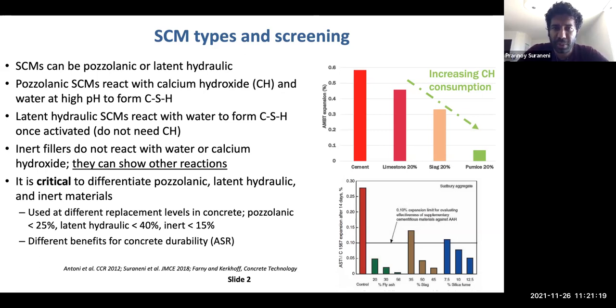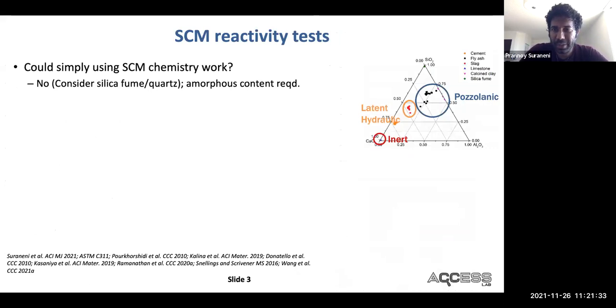But ultimately, you really want to separate out, when you have novel SCMs, their reactivity and what classification they fall under. Now, the same question of how we measure or screen reactivity comes back to us. So big picture, let's take a look at what we could do. Could we simply use SCM chemistry? A very simple thought experiment will indicate that this will not work, because if you consider silica fume versus quartz, both of these have the composition of about 95% SiO2. Silica fume is incredibly reactive. Quartz is completely inert. And the reason for this is, of course, that quartz is crystalline, silica fume is amorphous.